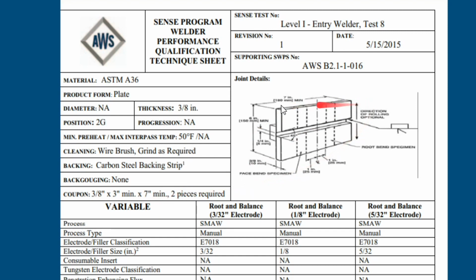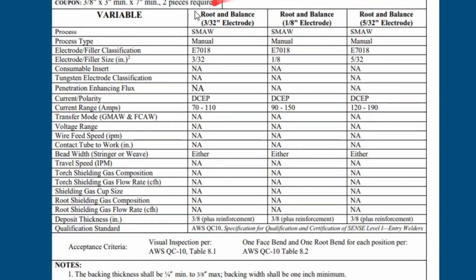7-inch total length. So we buy 7-inch stock. And then they give us some variables depending on what the student wants to use, what they're comfortable with. They can either choose a 3/32 electrode, an 1/8 inch electrode, or a 5/32 electrode. Typically, my students will run 1/8 inch electrodes. Every once in a while, I get a student who wants to run their root pass with a 3/32 and then switch to an 1/8 inch for their fill and cover. And that's fine as long as they stay within the variables.